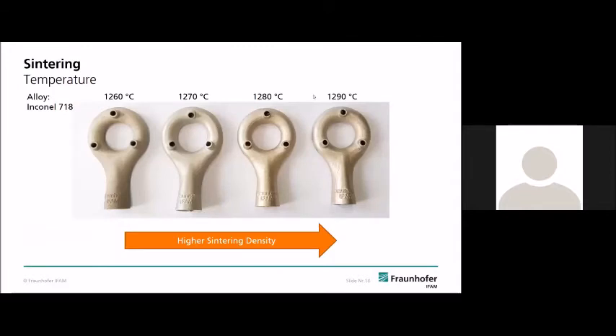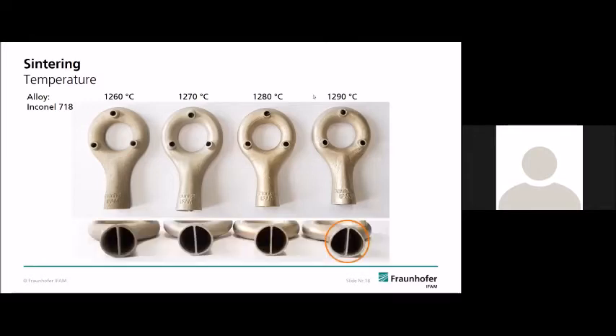The challenge with binder jetting is the sintering step, because sintering is a diffusion driven process and is very much dealing with sintering temperatures. So here we increase the sintering temperature in 10-degree steps, and you can see the differences here. If we get too hot during sintering, we lose geometry. So to use binder jetting, you should know how sintering works in general. And you should have some equipment for sintering, like special sintering ovens. Makes things a lot easier.